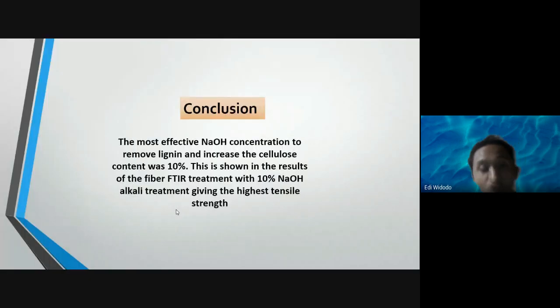The conclusion of our research is that the most effective NaOH concentration to remove lignin and increase the cellulose content was 10%. This is shown in the FTIR results of the fiber treated with 10% NaOH alkali treatment, giving the highest tensile strength.